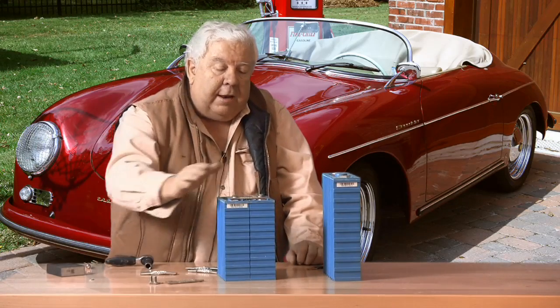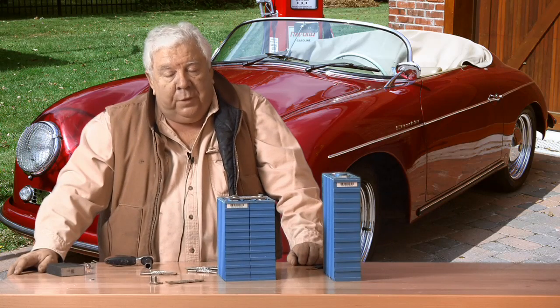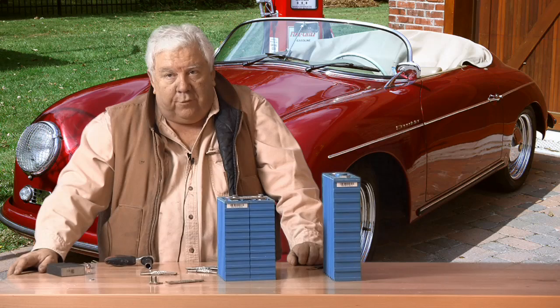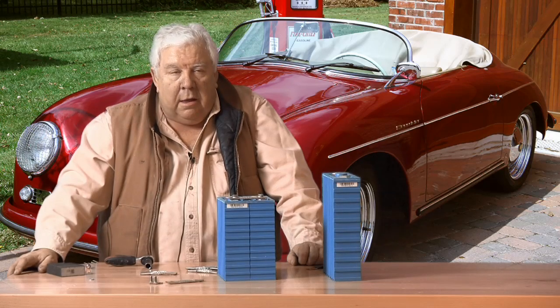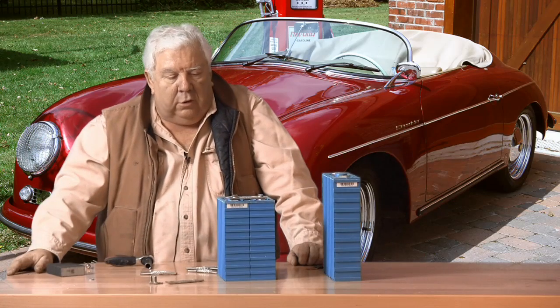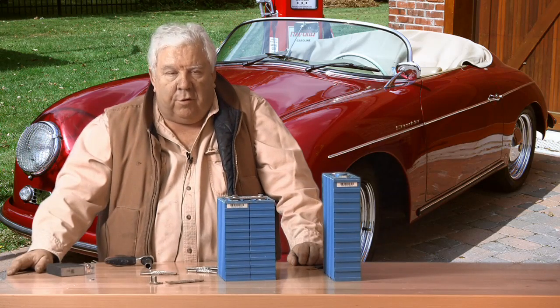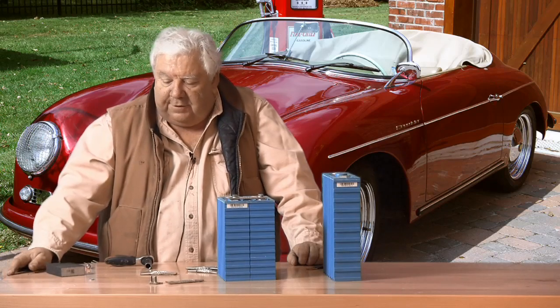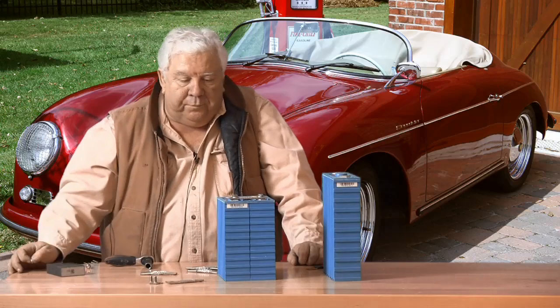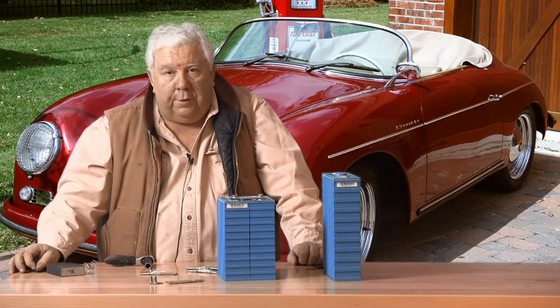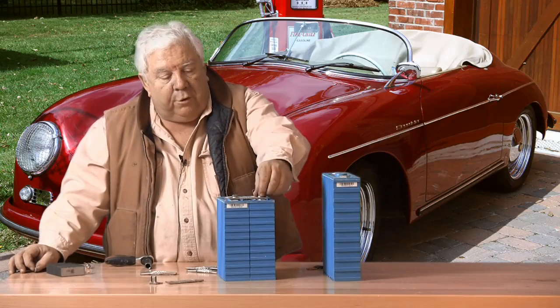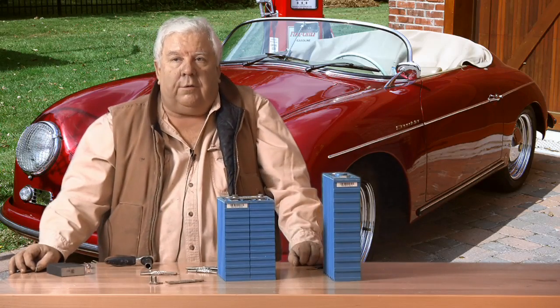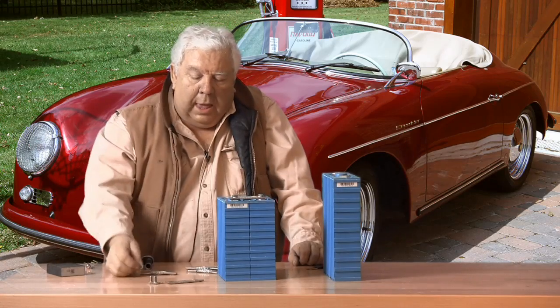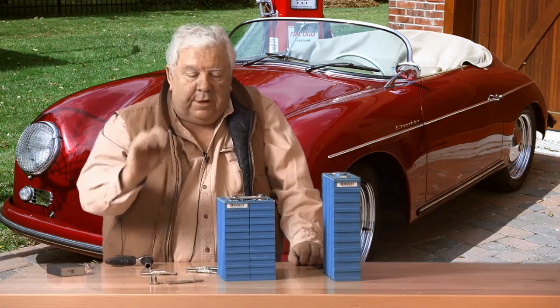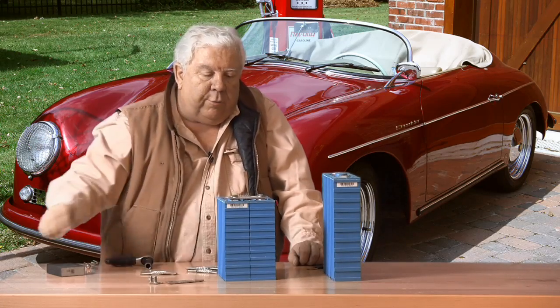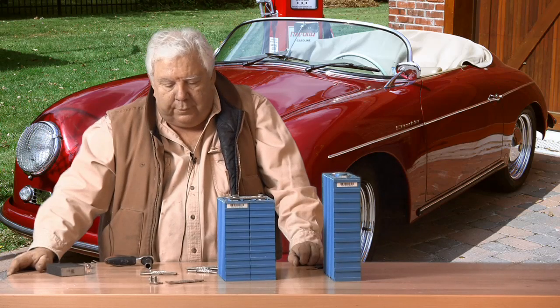So this makes a very flat connection. It doesn't corrode for a couple reasons. One, the strap is tinned, and the tinning is between the copper and the aluminum in your list of active or noble metals. And the lowest on the list is zinc, and our Nordlock washer is zinc coated. And so if anything in this pile of dissimilar metals is going to corrode because of galvanic action, it will be the sacrificial anode of the zinc washer, and not your strap, and not your terminals, and not your stainless bolt.